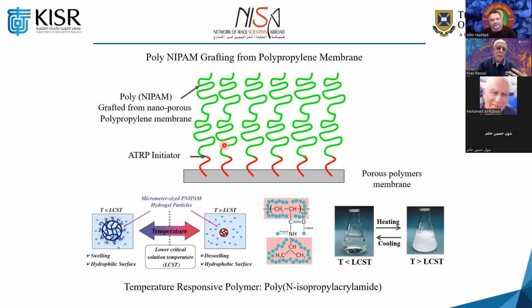So you will be able to build up a polymer onto a surface like this. Here we use polyNIPAM. This polyNIPAM is well known to have a very nice lower critical solution temperature, so this is LCST. If you take the polymer and cool it down, you find it becomes soluble in water because it forms hydrogen bonds with the water. But when you heat it up, it actually precipitates.